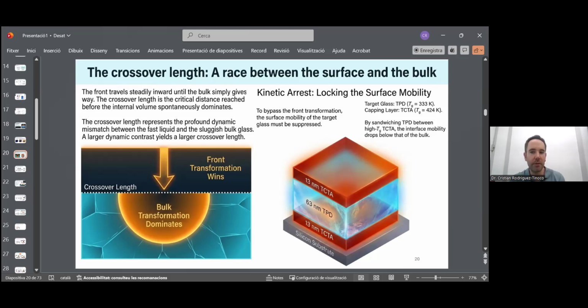Let's say we go to 340 Kelvin, for example, if we want to study how the TPD will transform. At 340, you see the TG of the TCTA is 424. At 340 Kelvin, the TCTA is still in the glassy state, very deep in the glassy state. The mobility in the TCTA is very low because it's in the glassy state. So this low mobility we have here in this interface will avoid the front transformation, will avoid the relaxation on the interface of the TPD with the TCTA. So this is a way of avoiding this front transformation.